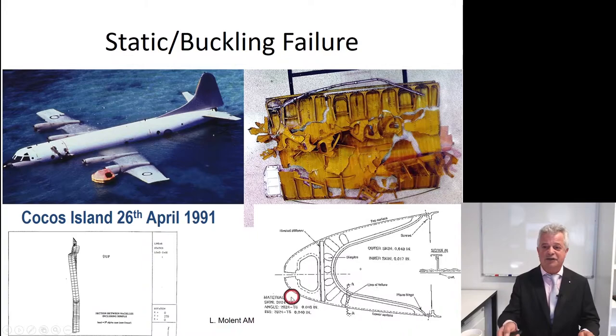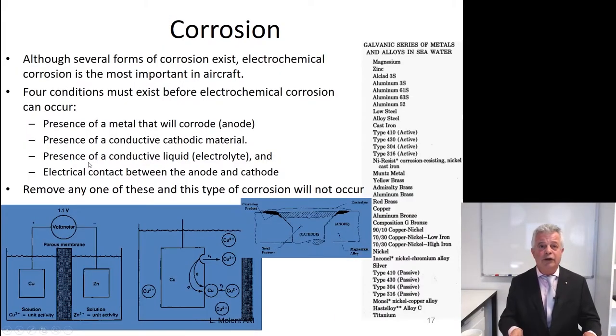And the highest stresses were along this chord station, and that's exactly where all the rivets failed. Here's a case where, yes, there was a slight overload, it wasn't excessive. Nevertheless, it did exceed the design envelope and buckling occurred, failure occurred, death occurred. Not good. Okay, moving on.